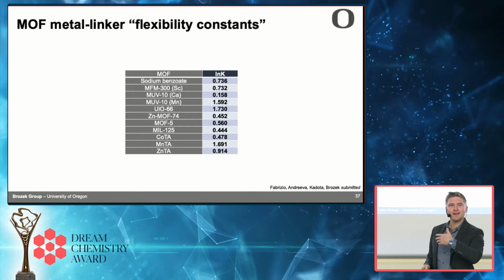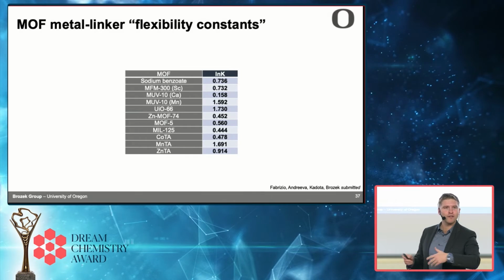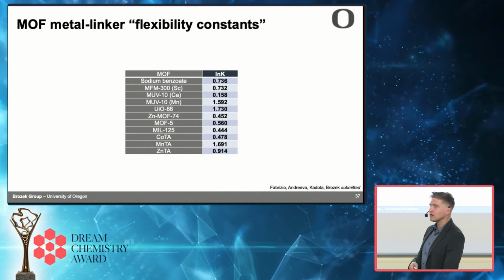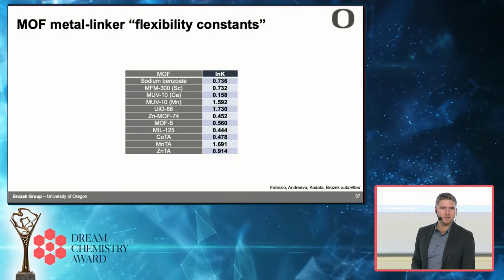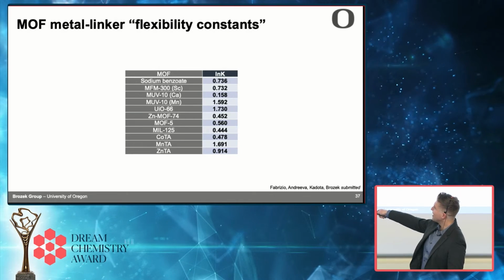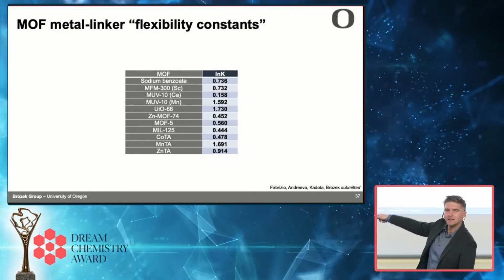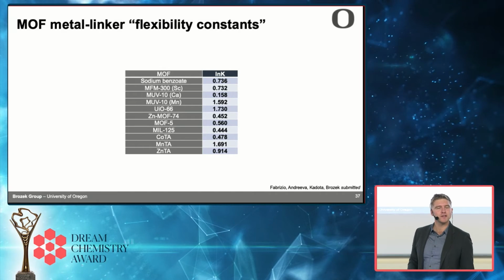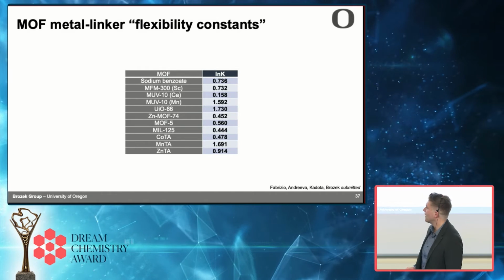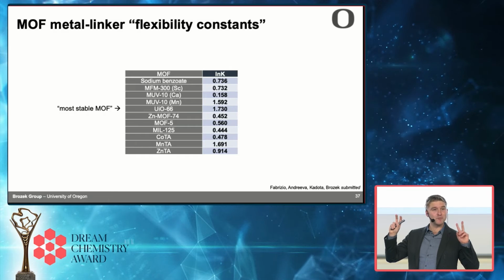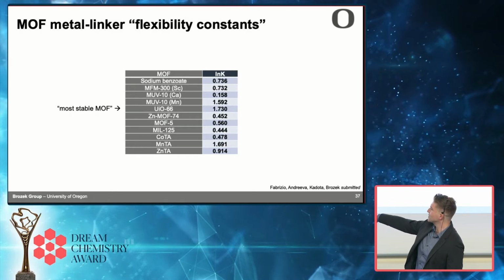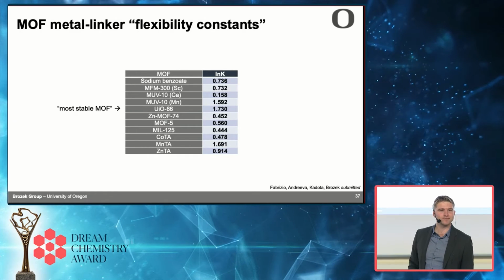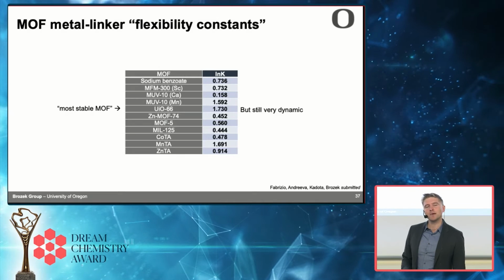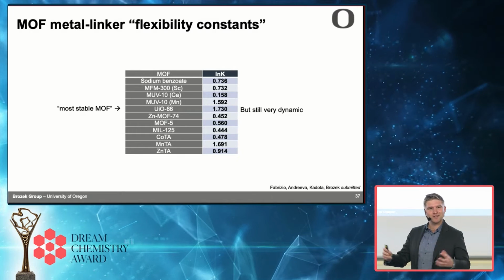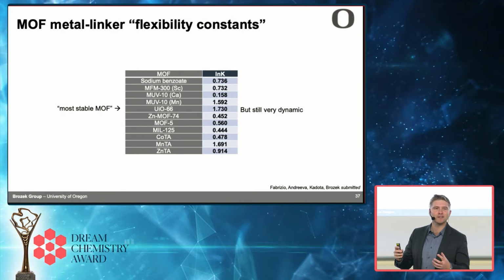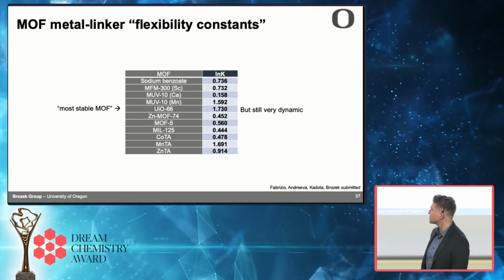And so now you can say, I'm working with some MOF for some catalysis purpose. Carl, how dynamic should I expect that material to be? So now I can say, well, okay, you're working with MFM 300. Now I can tell you those bonds are pretty dynamic compared to some of the others. It was nice to see that supposedly the most stable MOF, UiO-66, also has the largest stability constant. But it's not that big. So it implies that even in the most stable, what should be the most rigid materials, they still have this pretty strong temperature dependence.